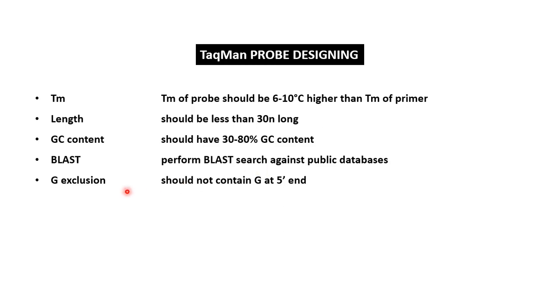Next is the G exclusion. As I already said, probe have reporter or fluorophore at its 5' end. And it has been observed that when the reporter is cleaved out of the probe by 5' to 3' nuclease activity of Taq polymerase, the 5' G, if present, will also be cleaved together with the reporter molecule and try to quench the fluorescent signal. Therefore, probe should not contain a G at its 5' end.